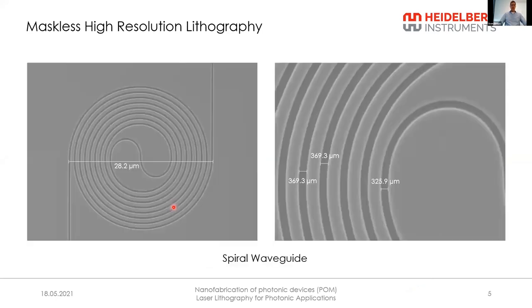If you go to more realistic patterns, this is the example of a spiral waveguide. You can see that we also get close to these 300 nanometers. Also, the uniformity is very good, and the lines are also very smooth, as you can see. So this was also written in raster scan mode, so it's a pixelated image that we write. It's not like we have a single laser beam that's simply writing this one line. It's really made up of pixels, and the uniformity and the line width is still very nice.